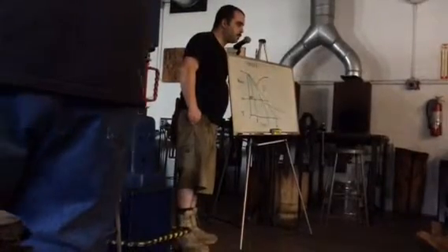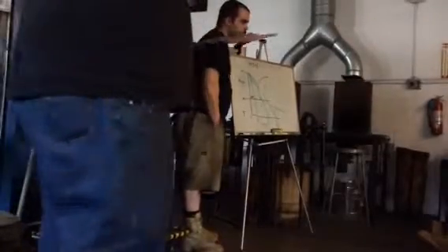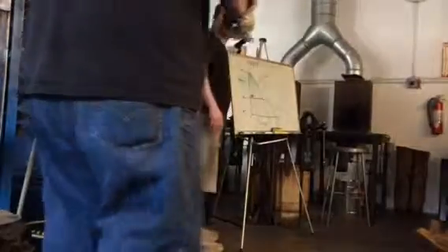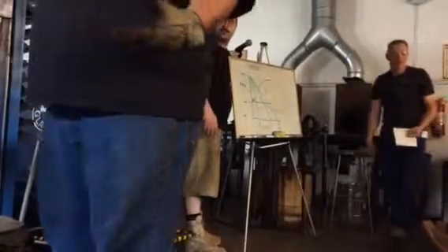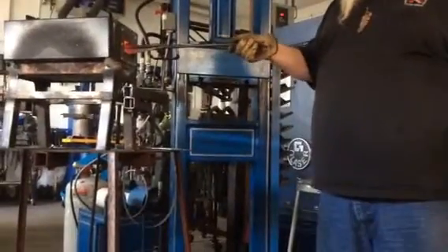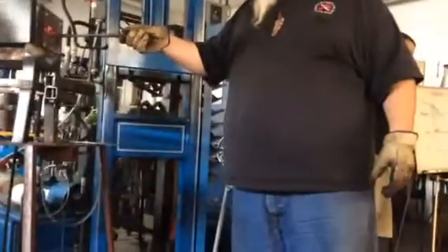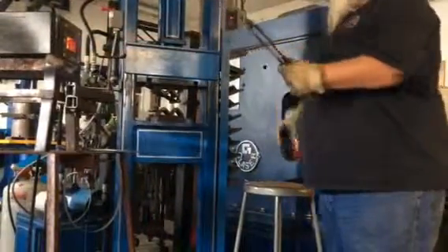Is there a point below which you want to get it before you heat it up again? Yes. The rule of thumb is not too high a heat. Yeah, black heat, so that's what I'm doing. I'll let it come down in temperature, but I'm maintaining some heat in that steel so that when I go back in, it doesn't take so long, and I'm not overheating edges and tips and stuff like that. What temperature is black heat? Like 800 or 900. Okay. In a very dark room, you can see color in steel, so like almost 800.